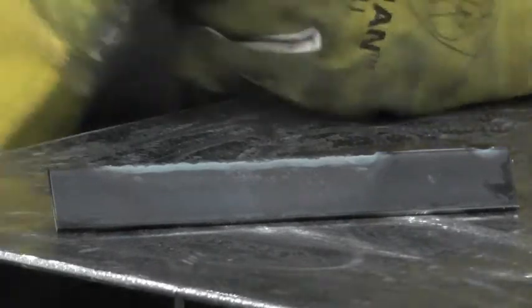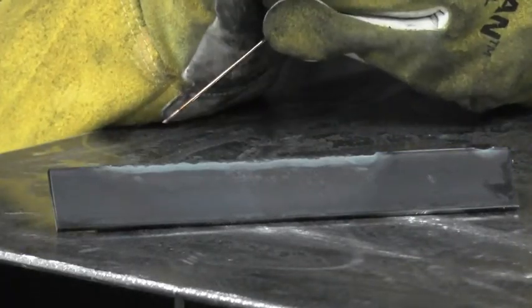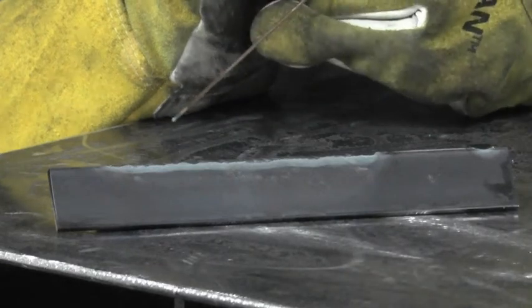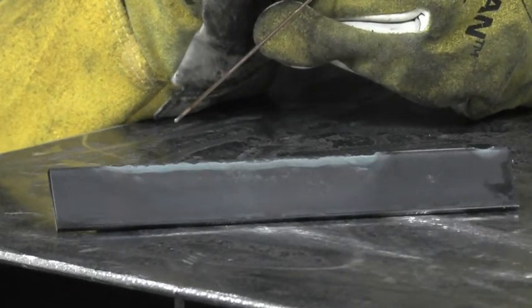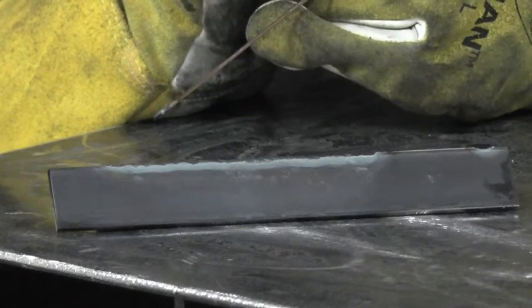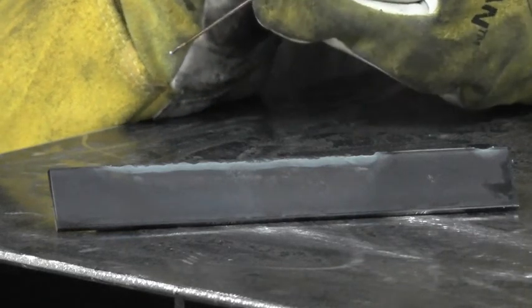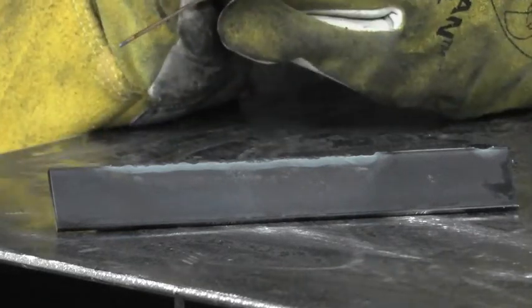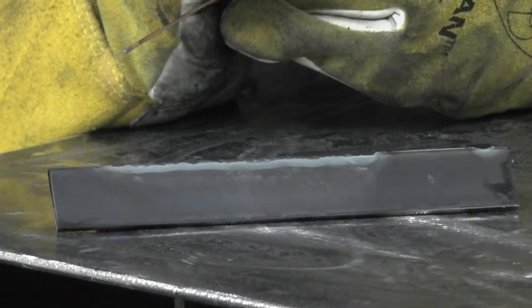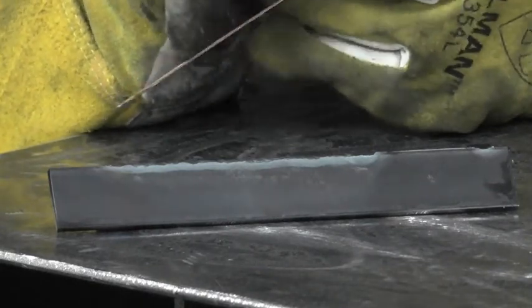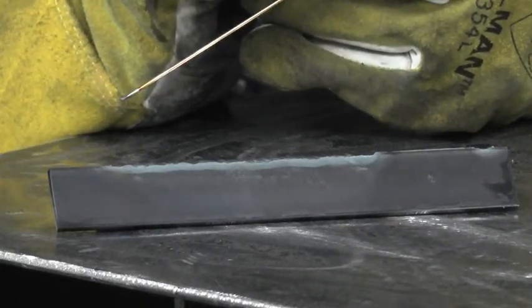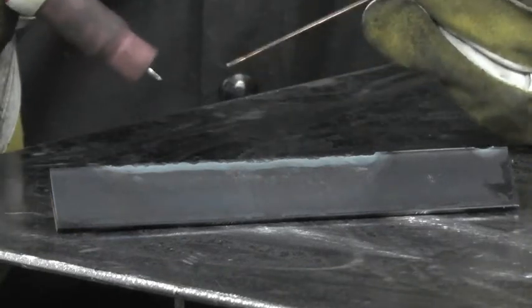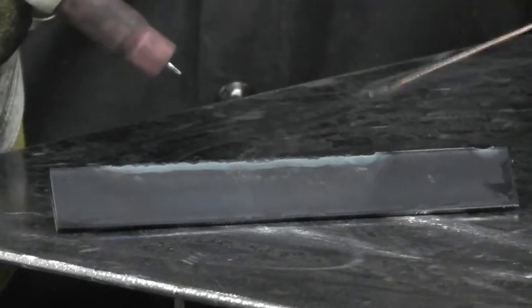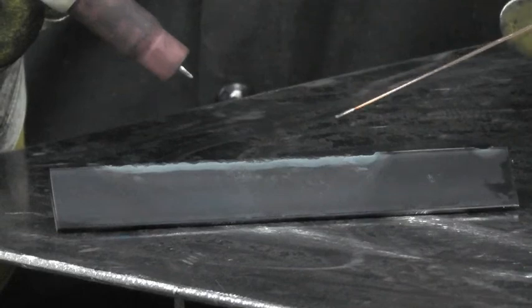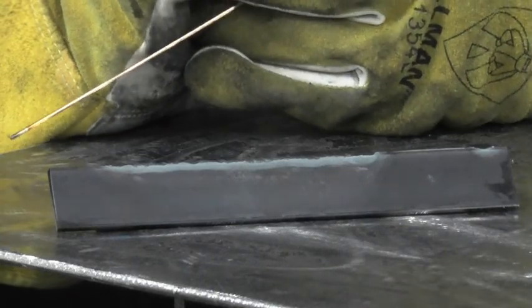That completes the demonstration on the TIG welding process. Again, my amperage is set at around 95 amps, right around 95 thousandths of an inch of steel, 0.095. Using 1/16 filler rod, doing the dip method, keeping your torch tip at roughly 45-degree angles, your filler rod at about 10 to 20-degree angle, doing the dip method down the outside corner joint.